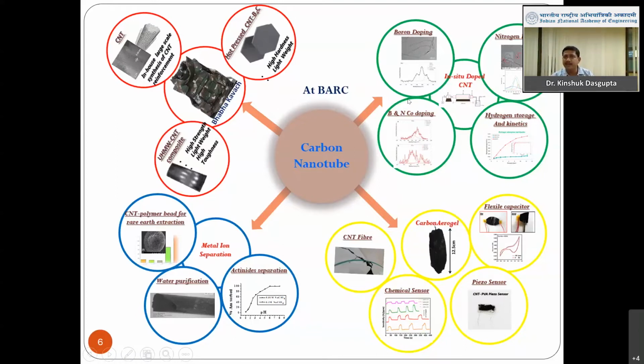And we can even dope heteroatoms like boron or nitrogen into carbon nanotube, and we can alter their properties, and that we have done here to understand how this doping helps in improving the hydrogen storage, and also we studied the kinetics. There is one special class of material which is called carbon nanotube aerogel. It is a 3D structure, self-assembled 3D structure of long carbon nanotubes, and this material also we are synthesizing, from where you can get carbon nanotube fiber.